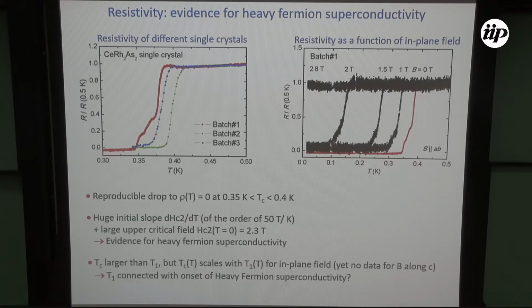Then we also look at the resistivity, and we look at different single crystal batches, and in all of them we found a superconducting transition between 350 millikelvin and 400 millikelvin. And we looked also as a function of magnetic field, and the initial slope is very large, so 0.5 Tesla almost doesn't shift the transition. And the upper critical field is of the order of 3 Tesla, despite the pretty low transition temperature. And this is the first evidence that it might be heavy fermion superconductivity.